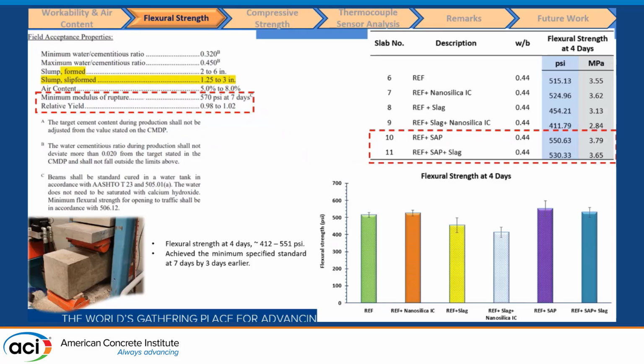Then for flexural strength, the beams were tested at 4 days because we are looking at how fast the road, if used in a road pavement or bridge deck, can be opened for traffic. So at 4 days we tested the beam, and the addition of SAP also improved the mechanical property, the flexural strength. At 4 days we were able to get 550 psi, that's the mixture with SAP. And from the INDOT standard specification for 2024, at 7 days the modulus of rupture, or flexural strength, was 570. So with the use of SAP, there's a possibility of opening the road 3 days ahead of time.